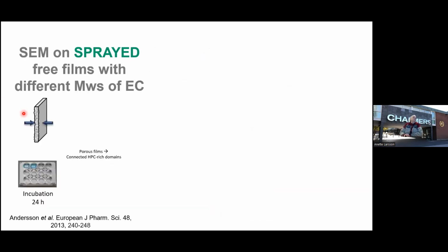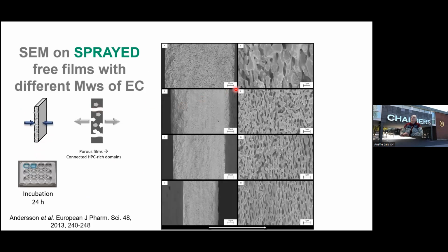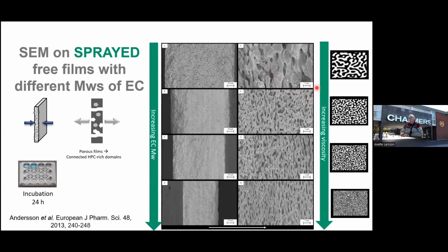So what we did was that we made free films. We placed them in water, and we had these structures, and with time in water, the HPC was dissolved. And then we freeze-dried them and looked into them to characterize the structures. And here we have an increase in molecular weight. You can see here the pores are much tinier compared to here. So this is where the HPC was before, but now it is an empty hole instead. And the reason why this happens is that when we have increased the viscosity, we lock them faster. So we arrest the structure earlier during the spinodal decomposition, which is then controlling the structure of the films.